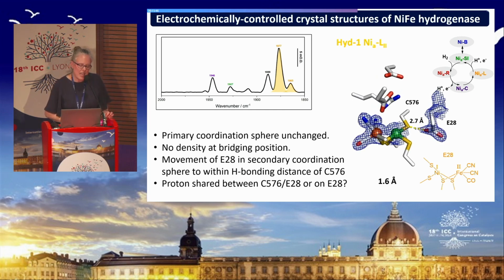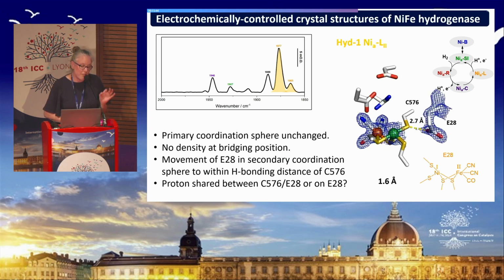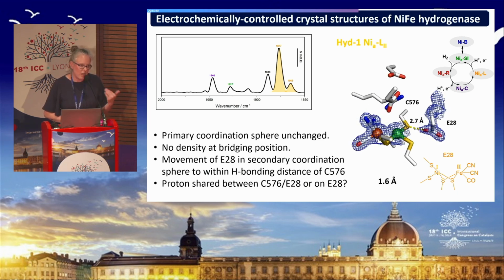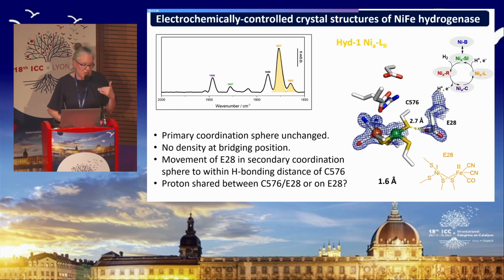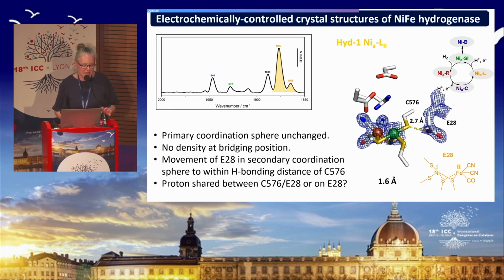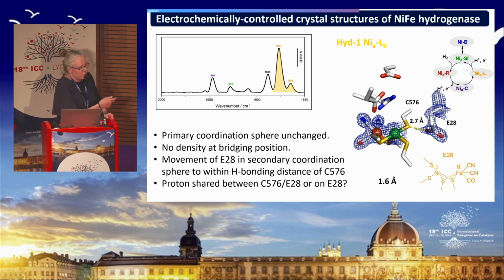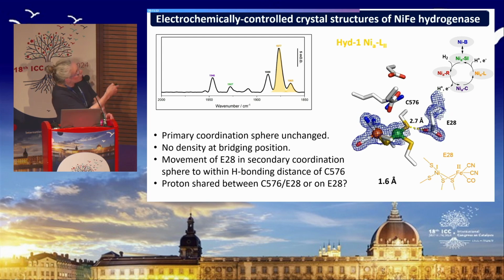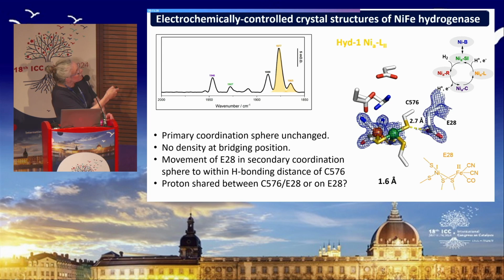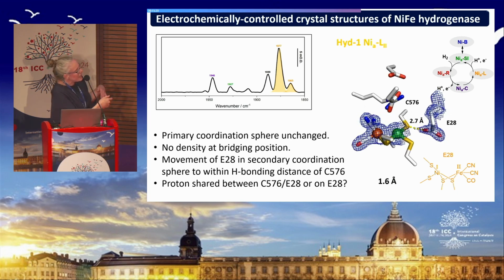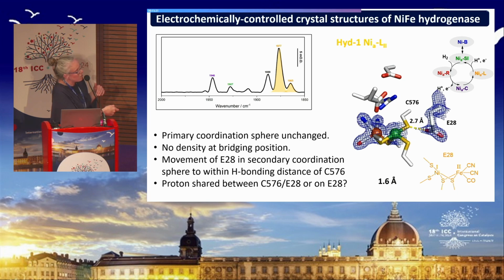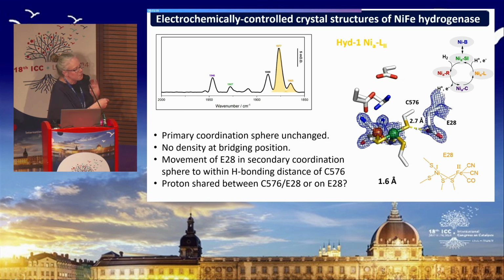In this case, we've now turned to hydrogenase 1 from E. coli, and this enzyme has stable nickel-L states which are present at room temperature and in the dark, so we don't need to illuminate to get to these states. And we've got a reasonably high proportion of nickel-L in the crystals. We always have a bit of some other states there as well, but we've got quite a high proportion of nickel-L here, enabling us to get a structure at reasonably good resolution of nickel-L.